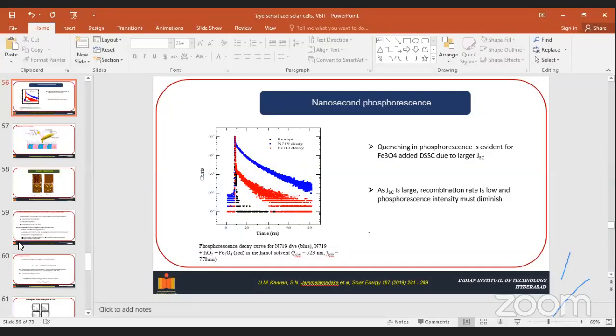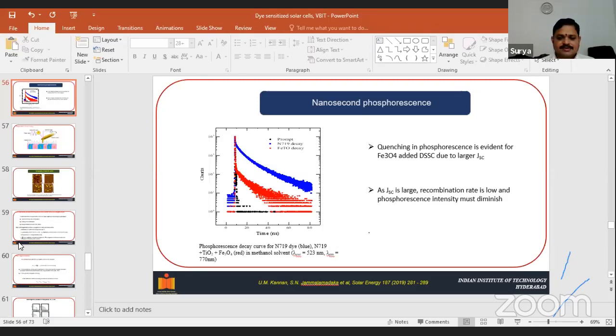The first question is posted by Dr. Srinivas Bura. He is asking what the important parameters to be considered are in the prevention of electron hole pair recombination. If you want to increase the electron hole pair recombination time, the most important thing is that they should not recombine. That is what we have addressed in this work. Basically, we try to enhance the electron hole pair recombination time by increasing the intersystem crossing. In the intersystem crossing, we try to unlock the transition between the singlet excited state and the triplet excited state. As a result, the electron spends more time in the triplet excited state, where you have longer lifetimes, and so the recombination time is enhanced.